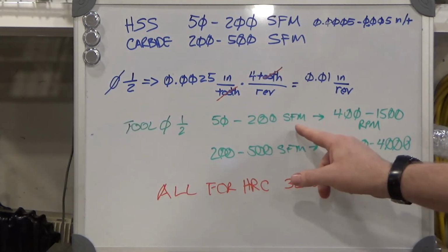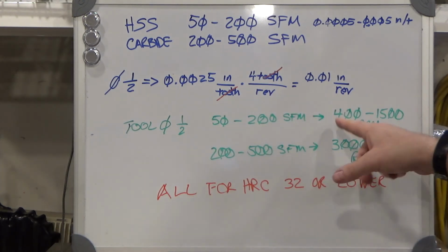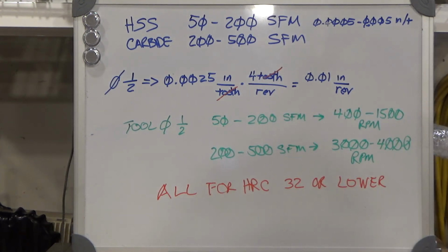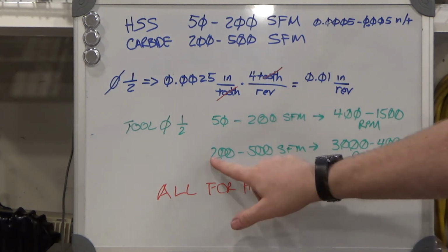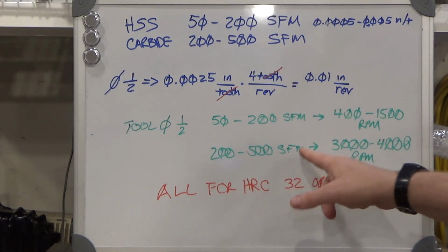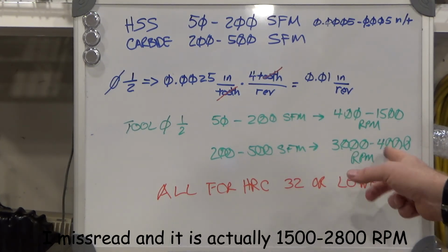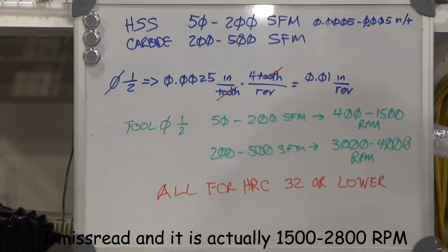So for a 1/2 inch diameter tool, since you won't be able to read this on camera, 50 to 200 surface feet per minute for a 1/2 inch tool equates to 400 to 1500 RPM. And 200 to 500 surface feet per minute equates to 3000 to 4000 RPM for a 1/2 inch tool, which is really fast for a home milling machine.